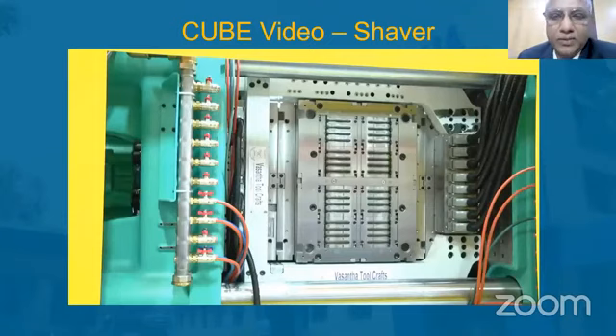Then this brown piece is put into a sintering furnace where we heat it up to almost 1200 degrees, based on the steel composition. And these products shrink almost 20-22%. In plastics, we talk about 0.5 to 1%, 1.5%, whereas in MIM, they shrink about 20, 22, 23% by size. Finally, it would be something like 99% solid density. This technology is very good if you want to make, for example, 50,000 pieces per day of a small metal part, having little intricate shapes and requiring good accuracies. There's no other method other than MIM, because you can't be cutting steel and machining those parts, which would be very expensive. So for any medium size or high batch production of small steel parts requiring good accuracies, this is the technology. All these technologies would be explained in detail in the next three sessions.